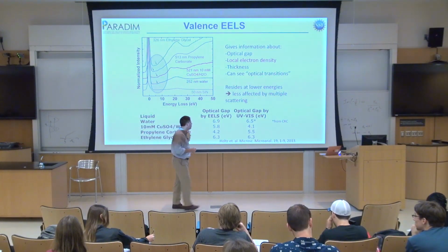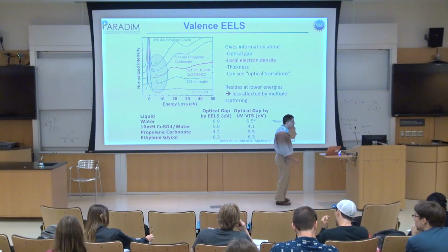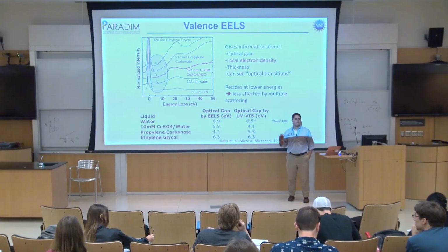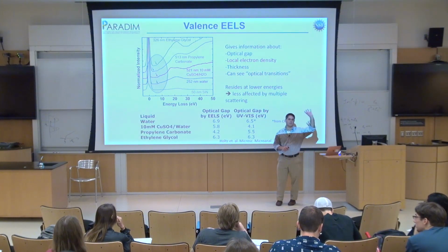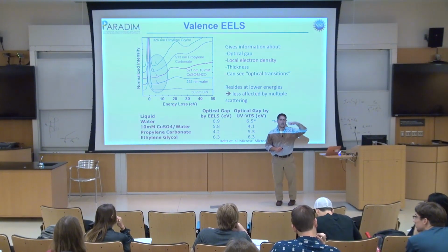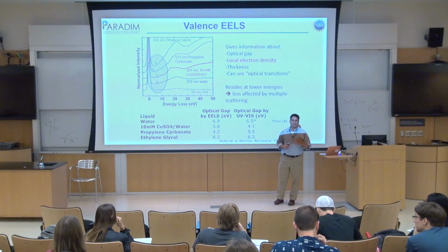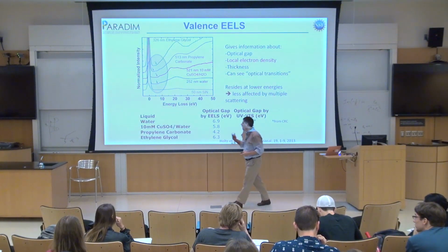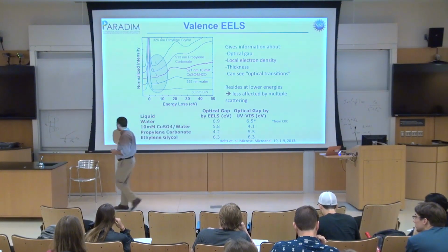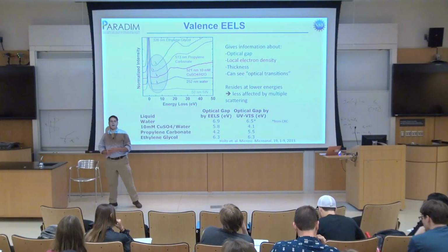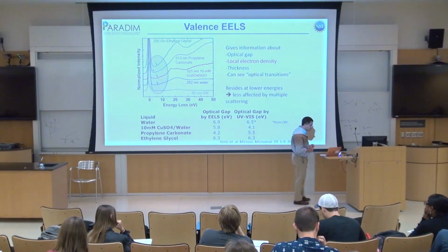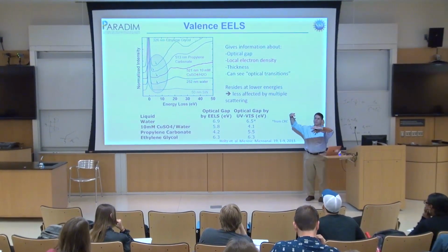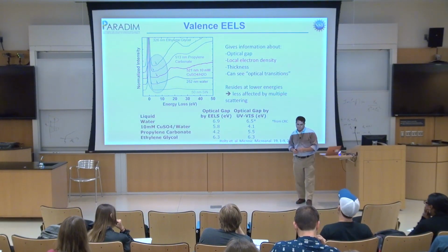Half the time we've tried to track down where discrepancies were in solids between our optical spectra and EELS spectra, it turned out the optical spectra had all sorts of defects and junk and states in the gap, and that extrapolated the tail incorrectly. The analytic form of what happens with an optical gap and trying to find it is actually quite tricky. You do these so-called Tauc plots, and you have to extrapolate lines because the edges are not sharp. So optically, it's a tough thing to do.